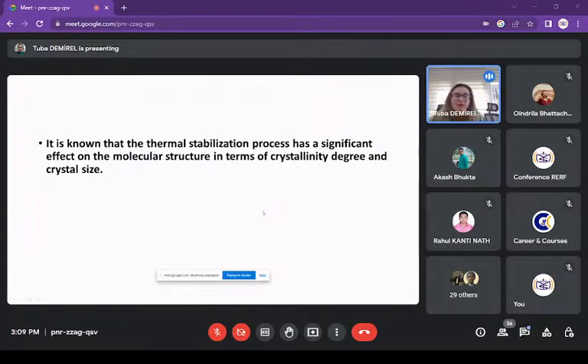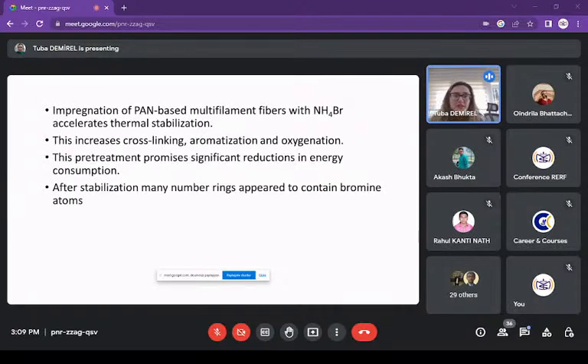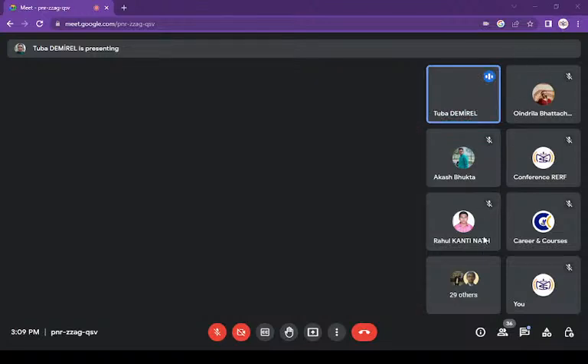Conclusions: it is known that the thermal stabilization process has a significant effect on the molecular structure in terms of crystallinity, degree, and crystal size. Impregnation of PAN-based multifilament fibers with ammonium bromide accelerates thermal stabilization. This increases cross-linking, aromatization, and oxygenation. This pretreatment promises significant reductions in energy consumption. After stabilization, many rings appear chained with bromine atoms.